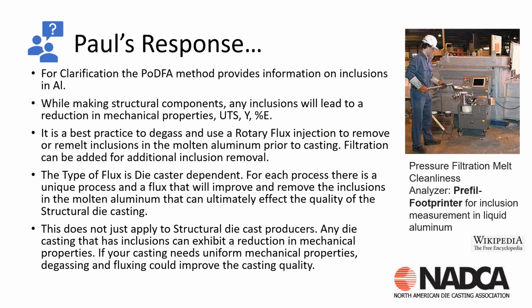Filtration can also be added, filtration between your furnace and either your launder system or your bull ladle. So you're going through a filter, and that is also going to remove some inclusions. Preventing the inclusions from moving from the melt downstream to the casting operation is probably one of the best practices. Understanding what those inclusions are, using the PODFA or the prefill, is a way to tell you where the inclusions are coming from. But actually removing those inclusions is probably the best method.